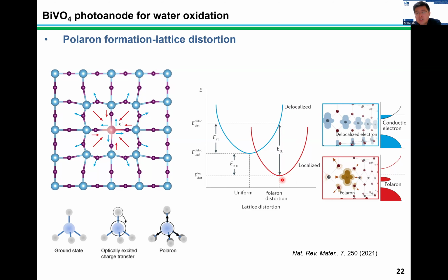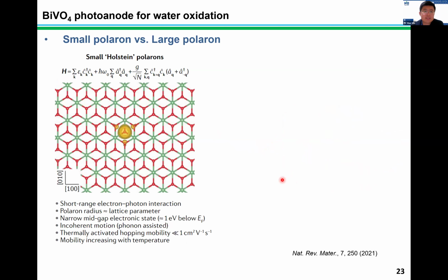we would like to contrast it with the large polaron. Small polaron, also called Holstein polaron, has an interaction radius generally just within 1 lattice unit, and it has a thermally activated hopping mobility with a value much smaller than 1 centimeter square per volt per second, and this mobility generally increases